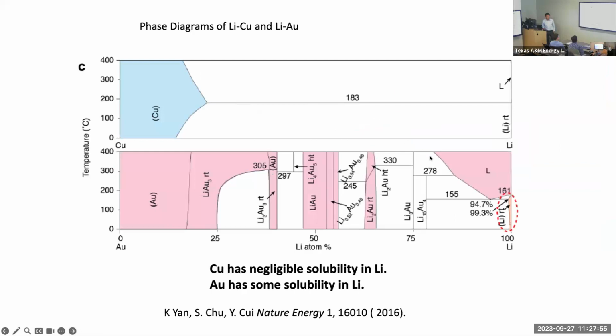So we look at this problem deeper. Actually, the phase diagram is teaching us a lot. On the top right here is between copper and lithium. At the bottom is gold and lithium. You look at the right-hand side, between lithium and gold. On the most right-hand side, close to pure lithium, gold has solubility inside metallic lithium, solid state, forming solid solution. What happens is lithium has this ability. If you deposit lithium onto gold, it will form one of these alloy phases, another of these alloy phases, and then lithium dissolves gold away, making gold more and more look like lithium before lithium deposition happens. There's no overpotential this way.